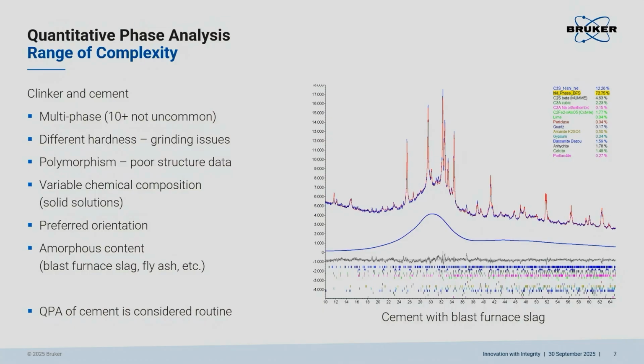There are often issues in such kinds of samples because the different components, the different minerals here, have a different hardness. And if you grind such a sample, what happens easily is that you destroy the softer phases. There's polymorphism for some of the polymorphs in cement. There's even no accurate structure data existing yet. You have variable chemical composition. So this is always an issue if you keep in mind that the Rietveld method requires crystal structures for each phase. Where do you get the crystal structures from? In case of doubt, from a database. But that is not necessarily representative of the structure you have in your sample. So a very important issue to keep in mind.